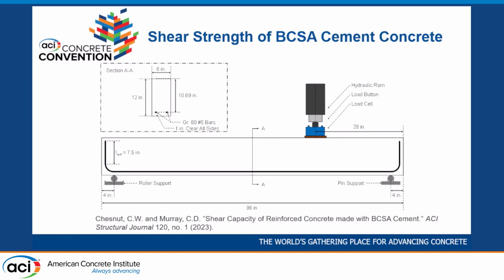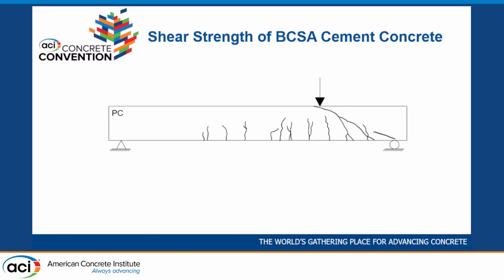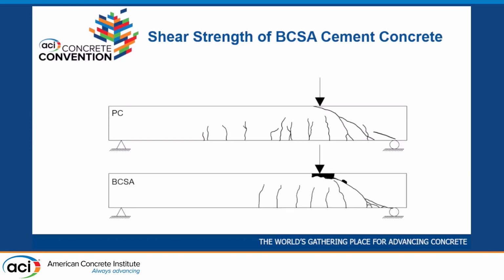After we did the flexural strength study, I had another student work on some shear strength. We made these beams with the same cross section as our flexural beams, 6 inches by 12 inches, but we put the load closer to the end. We used a shorter span, and you see there's no shear steel here, so we're just looking at the component of the shear that comes from the concrete alone. First we look qualitatively at crack patterns. This is one of the Portland cement beams, and here's one of the BCSA beams. All our failures were characterized by a big shear crack that went more or less from the load point down to the support. They were all very similar.